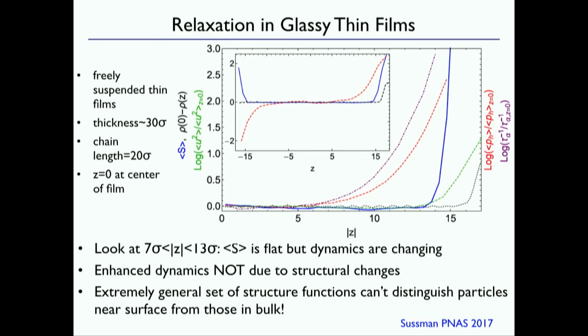And technologically, they're interesting because it turns out that you make glassy polymer films, plastic films, and you should be well below the glass transition. They should be solid, and actually they break. They pull apart because, since they're thin, their glass transition is actually a lot lower. And so they actually act like liquids. So the thickness of the film really has a big effect on the dynamics, and it's a barrier to applications of thin films.